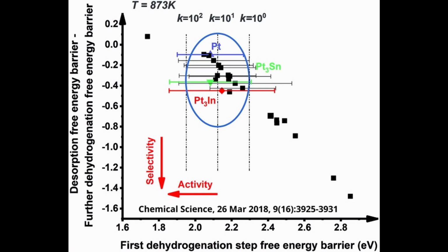A secondary effect of tin addition is the modification of the electronic property of platinum. Alloyed metallic tin or tin 2+ species in close contact with platinum are able to transfer electrons to the 5d band of platinum atoms, which alters the adsorptive and catalytic property of the metal.